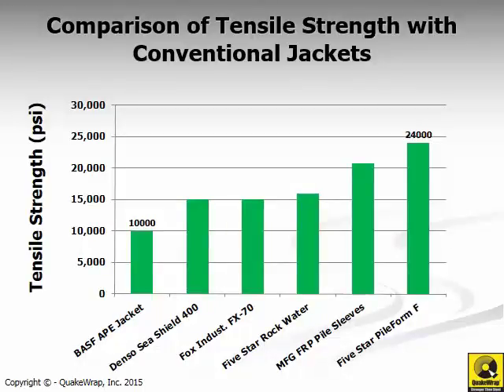In terms of strength, I have taken these values from the manufacturers' own websites, and you see that the materials that make these shells have tensile strength going from 10,000 psi to about 24,000 psi. Of course, even though they may have some tensile strength, you cannot utilize it for confinement of the column, because you always get a premature failure at the location of the seam or the joint.